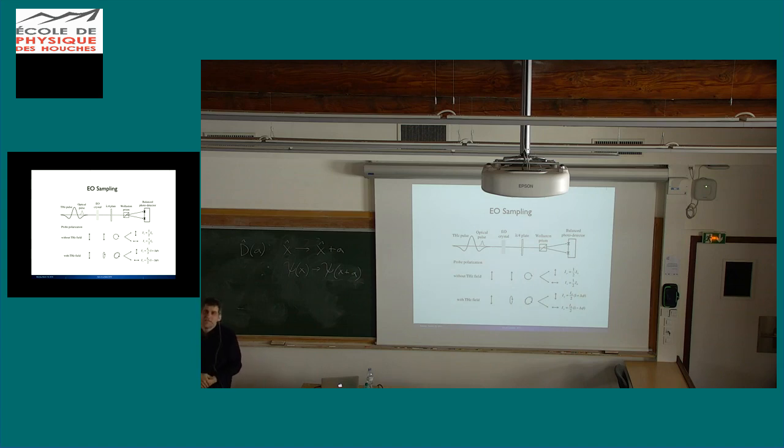Well, the advantage is that their nonlinear susceptibilities are much higher. The second order susceptibility is actually, I think, two orders of magnitude higher for those. That's because they have very complicated unit cells with a lot of weak bonding structure inside them. And so the second order susceptibility is just way higher. So that's the reason why people use them.